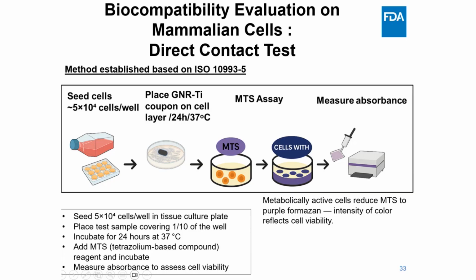In our setup, gold nanorod-coated titanium samples were placed directly onto a layer of mammalian cells and incubated for 24 hours, as shown in this image. To quantify the cell viability, we performed an MTS assay, which measures the metabolic activity of cells. Viable cells reduce the MTS reagent, a tetrazolium-based compound, into a purple colored formazan product, and the absorbance intensity of this color directly correlates with the number of metabolically active cells.